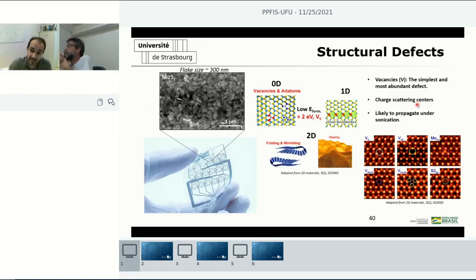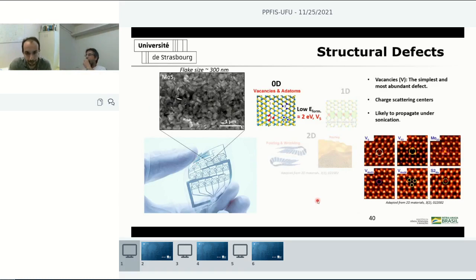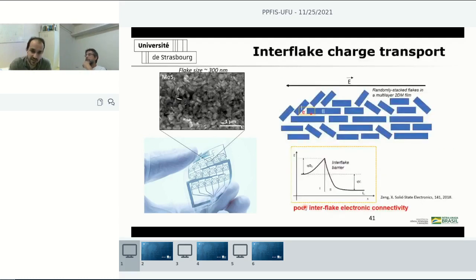And these vacancies, in electronic devices, can act as charge scattering centers. And during the exfoliation of these materials, for example, during sonication, they are likely to propagate, so you can have several defects per flake spread all over your film. And as I said, the most common is the 0D defect, the vacancies.